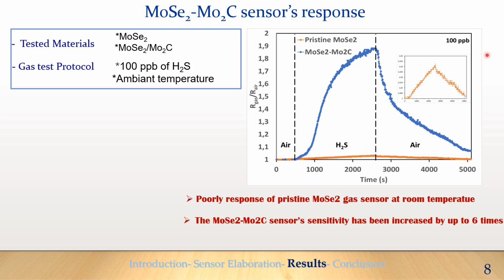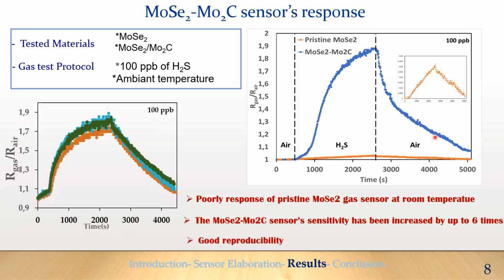It is noted that after gas injection, the resistance turned back to the original value when the sensor is exposed to air. The test of reproducibility on 3 sensors indicates that the sensor has good reproducibility and stability, validating the use of the drop casting technique to produce reproducible sensors. This first experiment highlights the use of MoSe2-Mo2C as a sensitive material for the detection of low concentration of hydrogen sulfide at room temperature.